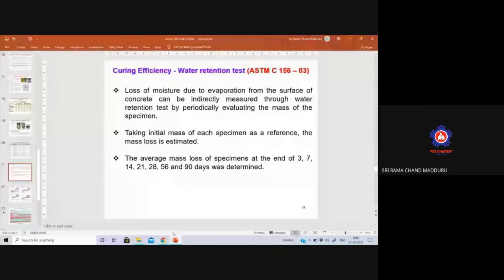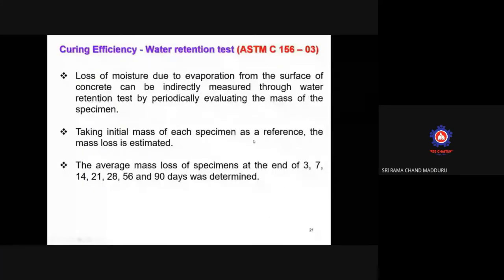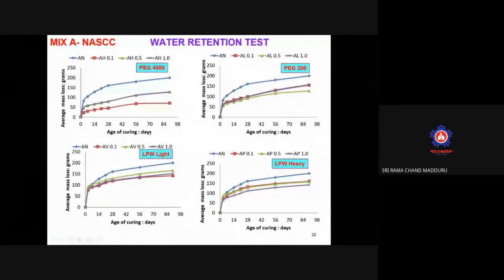So here, the water retention is nothing but you are measuring the curing efficiency by measuring the mass loss of the specimens at the end of 3, 7, 14, 21, 28, 56 and 90 days. So just see this diagram. I'm taking age of curing versus average mass loss. You can observe that AN is a representation for no curing. I didn't add any curing chemical.